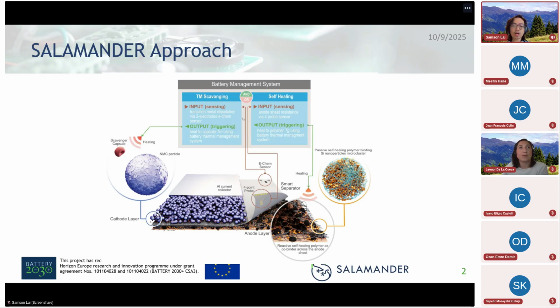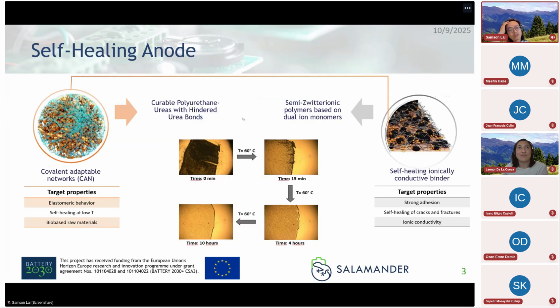So for the self-healing anode, as I said, we have two different polymers. One is this covalent adaptable network. This is a type of polymer that has very nice elastomeric properties. You can make films of it, and it's stretchy. In the figure in the middle, you can see that there's a cut that's made, a macro scale cut. This is optical microscopy, nothing very high resolution. But with some application of modest temperature and time, you can actually see this cut heal itself. And so the idea is this is how the polymer can heal different cracks or different damage to it.